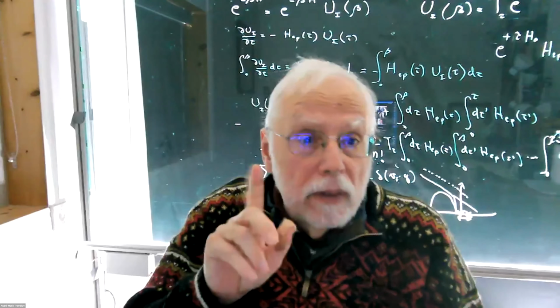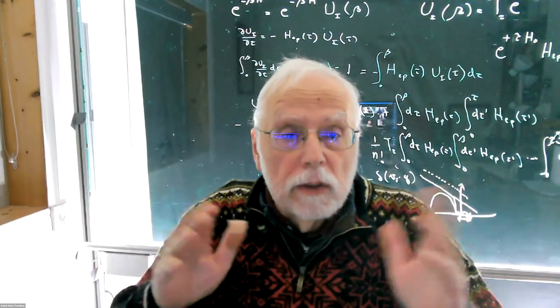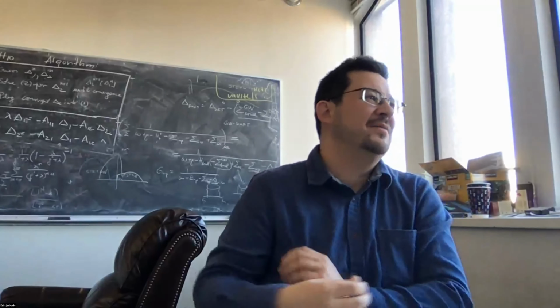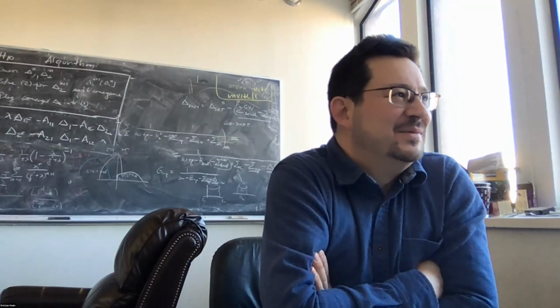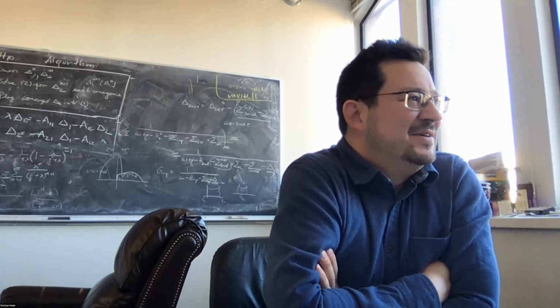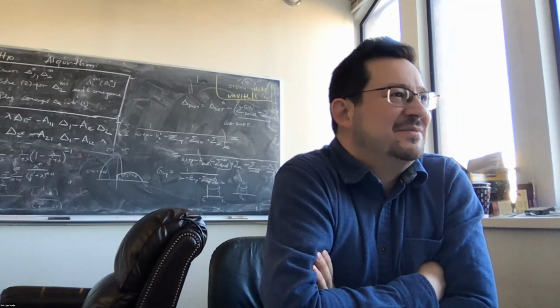Maybe I can just get everything going. Just to step back, you've highlighted the fact that the three-band model can delineate between D doping and P doping, which I think is very, very interesting. But the one-band model does also, because the band structure is not particle-hole symmetric. Yeah, there's different T prime. But superconductivity is wrong, in the sense that it's small on the hole doping and somewhat larger on the electron doping.